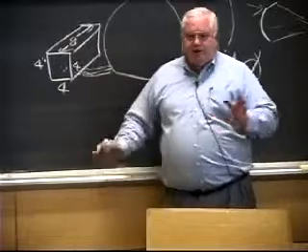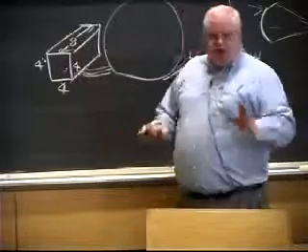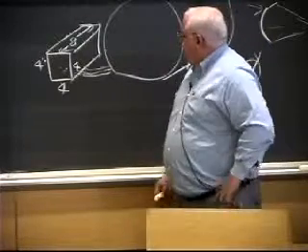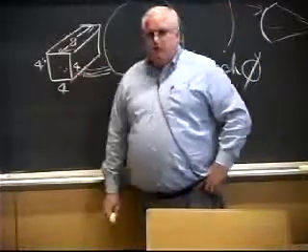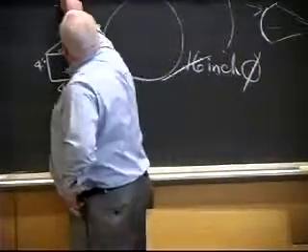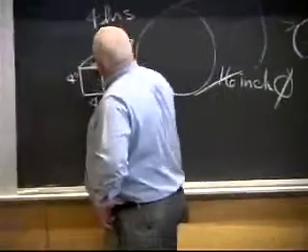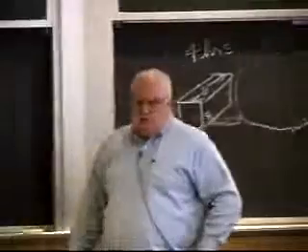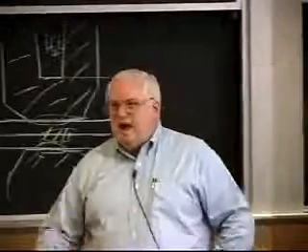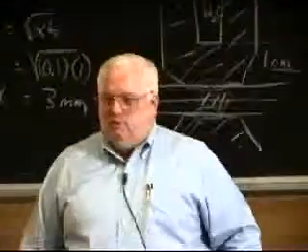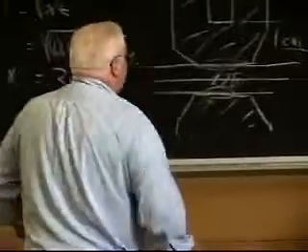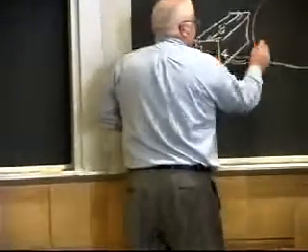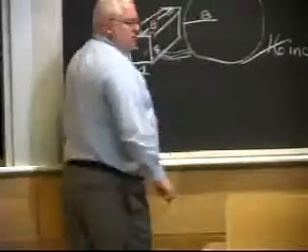Okay, so they cast these things, and then they have to heat treat these things to, as they call it, normalize the steel structure. So this casting shop puts these in the furnace for 4 hours. Puts this one in the furnace for 4 hours, puts this one in the furnace for 4 hours. The question is, is that an adequate amount of time? Well, it's steel, so I have a distance here of 2 inches that I'm interested in. I have a distance here of 8 inches.